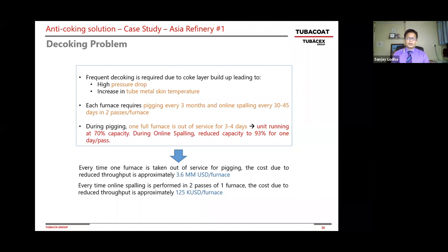So they have a frequent decoking as required due to coke buildup. One, because of the high pressure drop. Second is the high tube metal skin temperature. And they take out each furnace out for pigging every 3 months, and also online spalling every 30 to 45 days. And they do 2 passes per furnace, and they have 6 passes per furnace. And during the pigging, their capacity is reduced to 70%. And during online spalling, their capacity is reduced to 93% while they do the spalling.